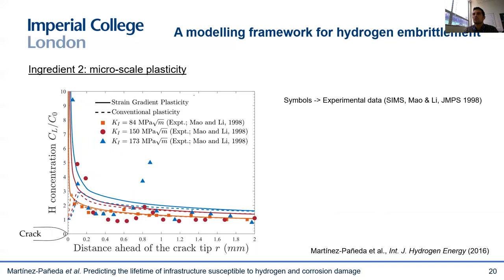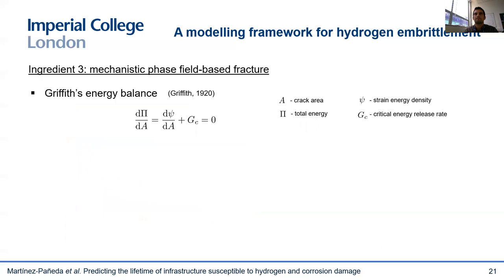Now let's turn our attention to the interface. When does a hydrogen crack start, and when does it grow? For this, we use the phase field method. The question becomes: what is the differential equation governing the evolution of the phase field? In the case of the crack-solid interface, one of the beauties of this method is that it provides a platform for the energy balance of Griffith, which gave birth to the discipline of fracture mechanics. Griffith postulated that a crack will grow if the energy stored in the solid is sufficient to overcome the energy required to create two new surfaces.